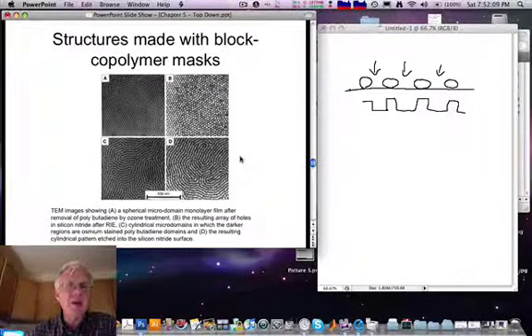On the left are the domains after the removal, in this case of polybutadiene, leaving spheres of polymethyl methacrylate behind. And then after this surface is etched, B shows the little posts of, in this case, silicon nitride after reactive ion etching. Cylindrical domains can be made with the appropriate deposition of polymer, and in C, the cylindrical domains have been marked by staining with a heavy metal stain, osmium, and the cylindrical patterns transferred to the underlying silicon nitride surface after the appropriate etching steps.